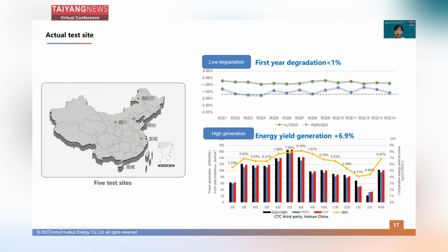And regarding the energy yield generation, the HJT module will have around 6.9% increase compared with the PERC modules. And we can see that in last August, the energy yield generation increase was already exceeding 8%, which means that the lower module temperature coefficient is the main factor helping to increase HJT module energy yield generation capability.